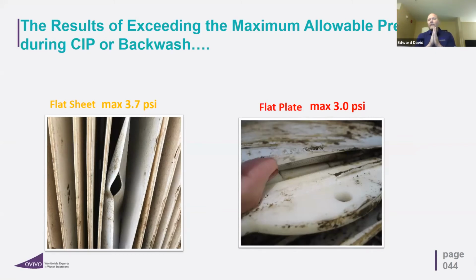And on the right side on the flat plate, even though it is adhered to a stronger substrate, it's only supported around the perimeter of the filter material itself. So what you're doing is you're going to separate that weld from that hard material, and it's going to make a breach. And if you ever get a breach on polymerics and you don't catch it, it will migrate. The solids will migrate up and into the permeate header, and then between that breach and your pump, all the other membranes, all the other sheets and the modules associated with that will fill up with sludge. And again, that's not something you ever want to experience.